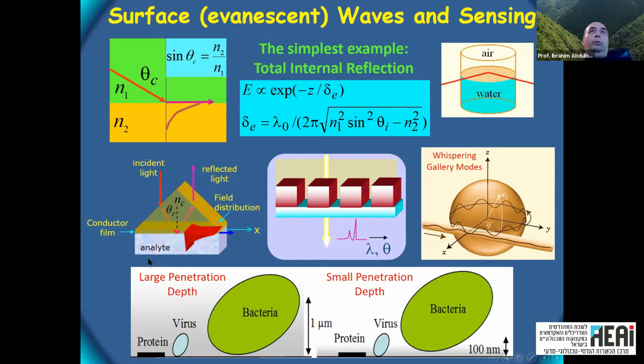For example, what we are talking about now is when we have a metallic film, we excite the plasmonic wave, and it's a wave propagating along this surface, but cannot propagate perpendicular to the surface. So it has an evanescent field, and this evanescent field can feel what's happening near the surface within the penetration depth, of course. So this penetration depth is highly important as it can easily sense small entities like molecules, proteins, viruses.